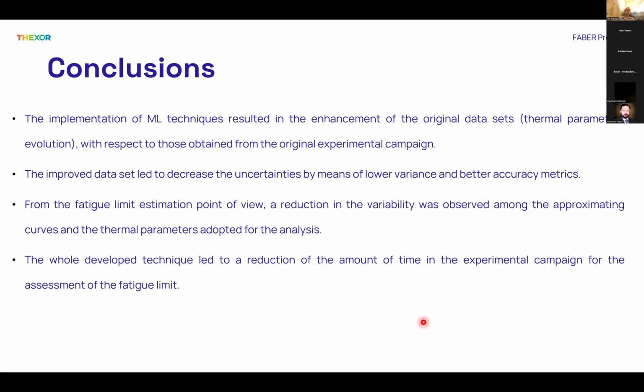Actually, if I want to say one of the accuracy metrics that were derived in this research, we developed the R-squared from 91% to 97%, or we decreased the RMSE on the thermal parameter by near 60%, from 0.019 to 0.008. So these are the main conclusions on the side of ML that enhance the dataset.